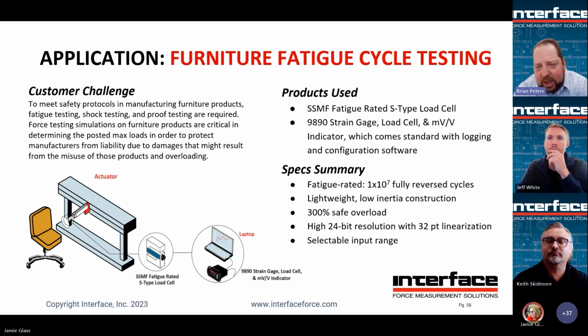In this case, it was paired with a 9890, good high resolution 24-bit sensor or instrument, and that even actually takes up to 32-point linearization. So a customer could really dial in that force curve if they wanted to. And again, selectable input range. So if you want to maximize the internal A to D conversion, and using this with different sensors, you can dial in that input range so you keep the most resolution there possible as you may move from one input to the next. Next.